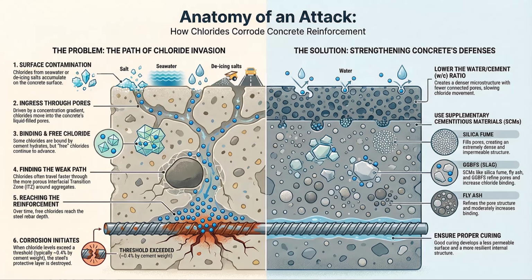I can imagine. When you take field samples and analyze them, identical concrete mixes, same recipe placed in the Saudi Eastern Province or the UAE marine zones, show a diffusion coefficient that's 2 to 3 times higher than that same mix would have in a cold climate. The mix is the same, but the environment has just made it exponentially more vulnerable. Exactly. And here's a critical detail that often gets missed.